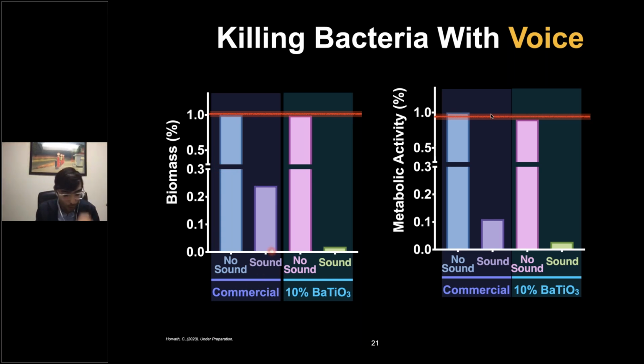If we do commercial only with sound, there's a reduction in the amount of biomass, and also a reduction in the metabolic activity. And when we look for the same with the BTO or the piezoelectric composite, we have an augmented reduction of the biomass and an augmented reduction in the metabolic activity. So sound by itself is antibacterial, but when we use these piezoelectric materials, we actually increase the antibacterial effect.